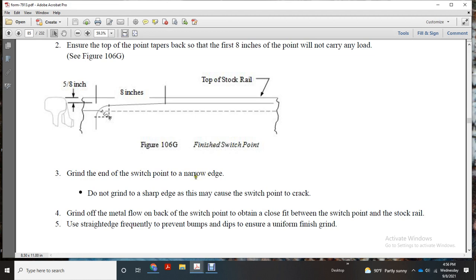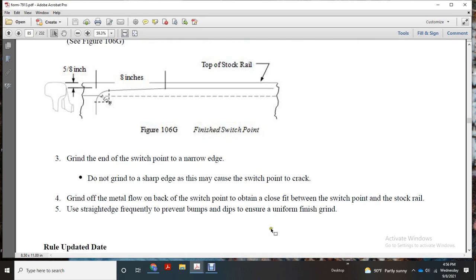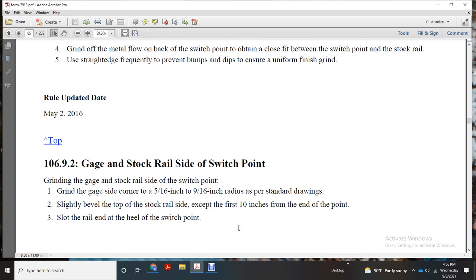Grind the end of the switch point with a narrow edge. Do not grind to a sharp edge as this may cause the switch point to crack. Grind off the metal flow on the back of the switch point, to obtain a close fit between the switch point and the stock rail. Use a straight edge frequently to prevent bumps and dips and ensure a uniform finish grind. Gauge and stock rail side of switch point.